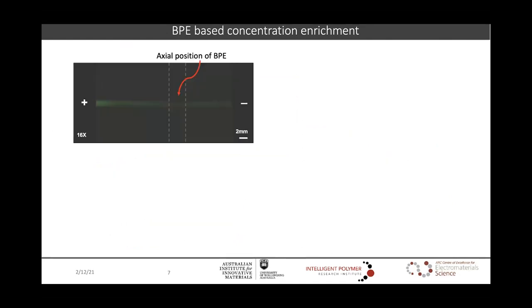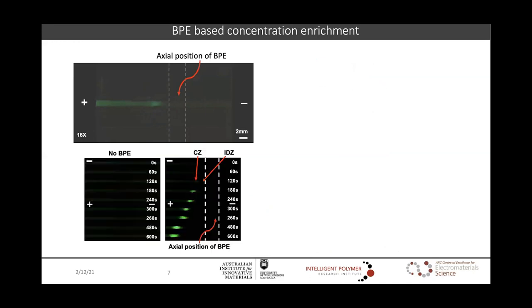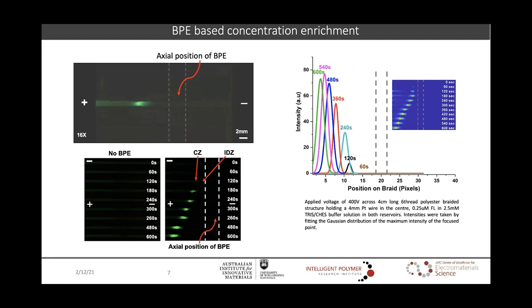To demonstrate this, we filled the textile channel with anionic fluorescein in Tris-glycine electrolyte solution, and on application of an electric field, an ion depletion zone is generated near the cathodic end of the BPE, which results in an electric field gradient in this region that concentrates the anionic fluorescein and migrates it to the respective anodic reservoir. On quantification, we can see that concentration increased with the passage of time until the solute moved to the edge of the reservoir.